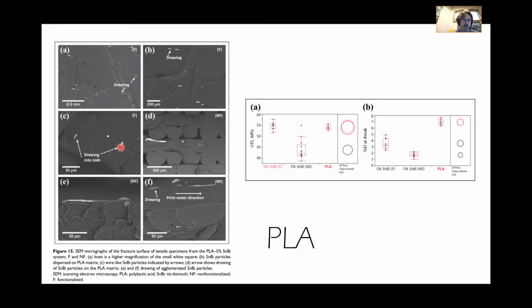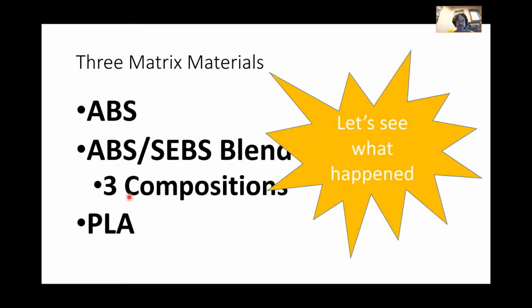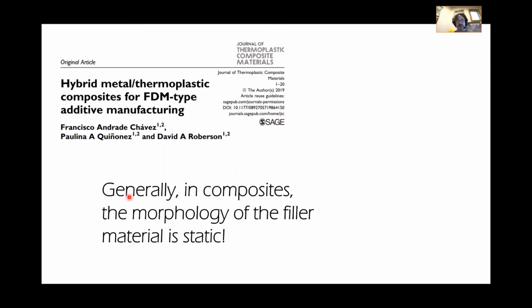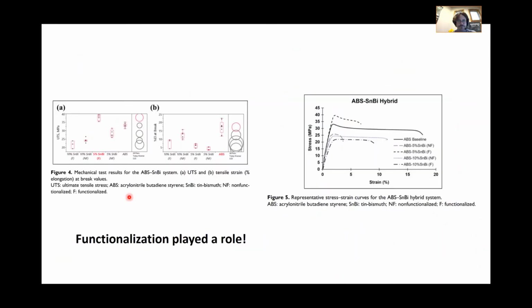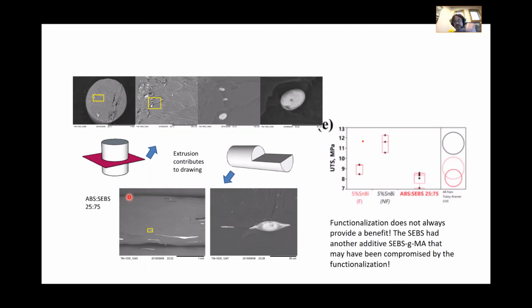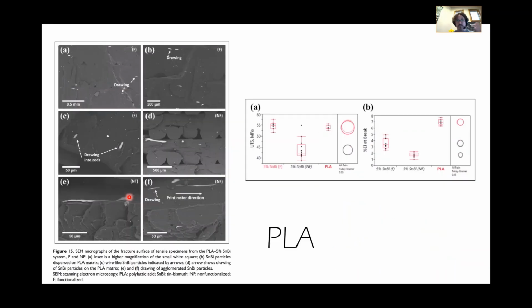But if you look close, we actually drew rod-like structures. So the drawing was more profound in the PLA than it was in our ABS or ABS-SEBS blend. The matrix material interaction with your filler material, whether it's sticking, whether in this case we're doing a hybrid material - I should point out this was published in a Journal of Thermoplastic Composites, so it's quite fitting. The interaction of the matrix material with your filler material, whether it's a sticking thing or changing the morphology based on some sort of viscosity thing, are all aspects you have to consider.